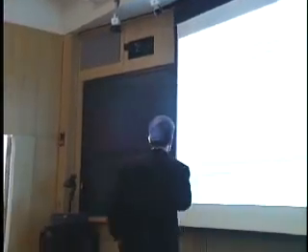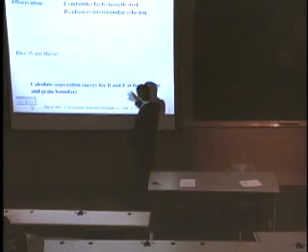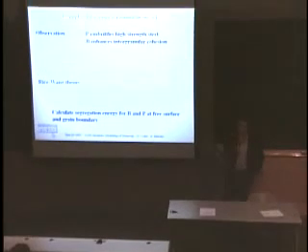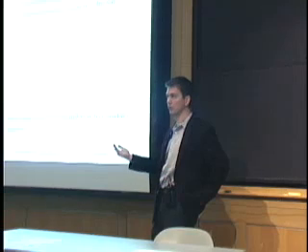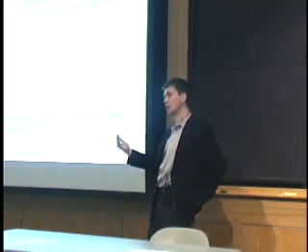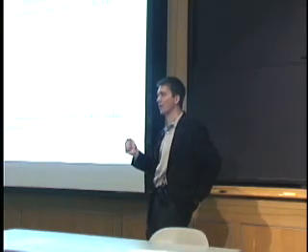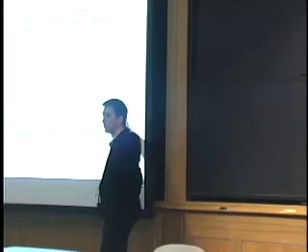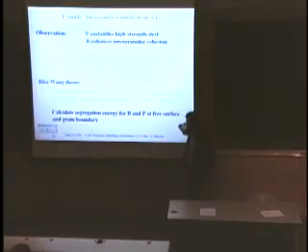And that's the Rice-Wang theory, which essentially states that the embrittling tendency of a solute depends on the difference between the segregation energy for that element to a grain boundary and to a free surface. This is actually mathematically justified. It's a quite elaborate theory that you can catch in 2 sentences. But you can see why this is true from a driving force perspective.